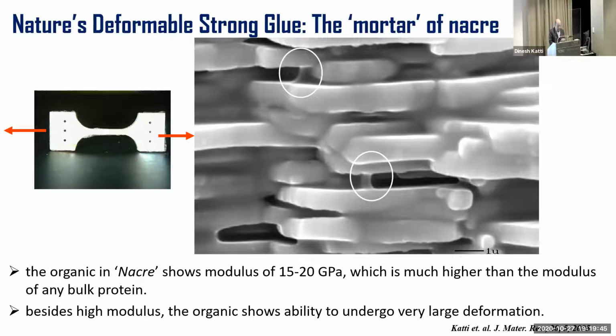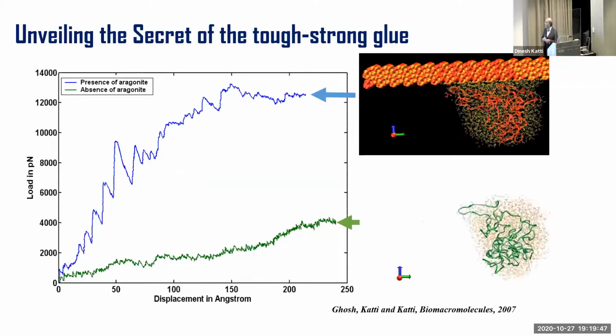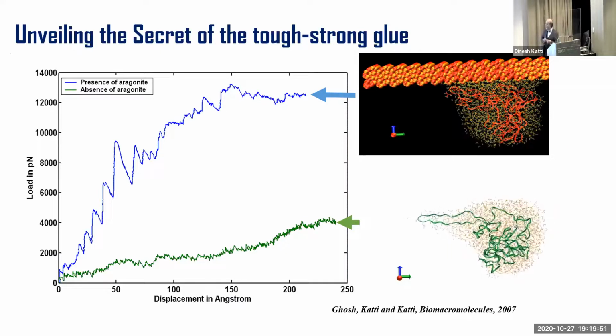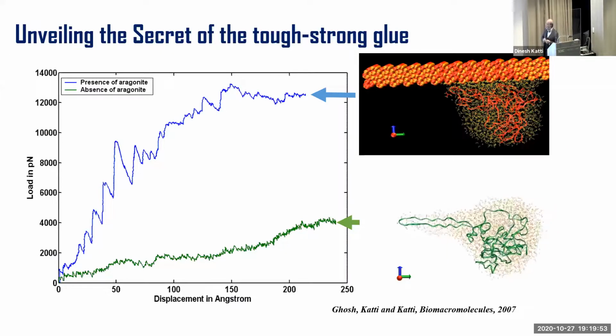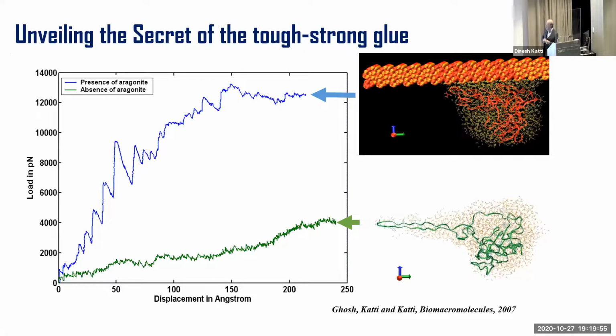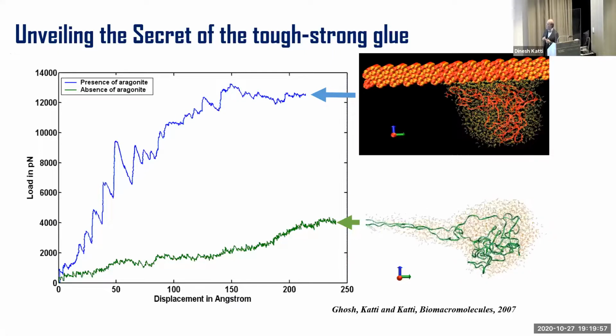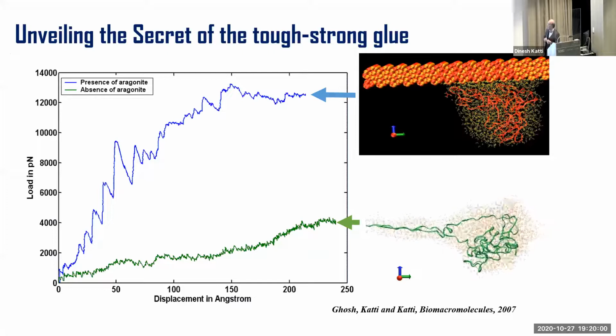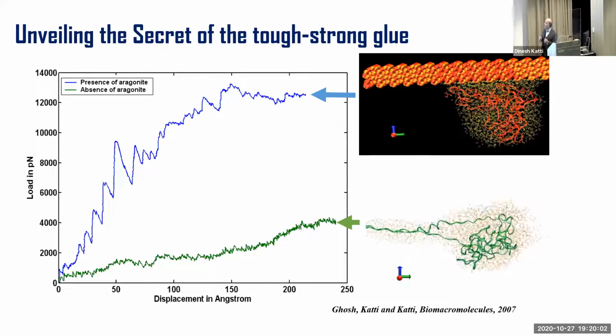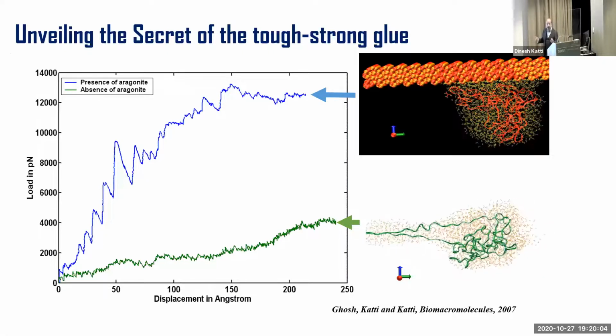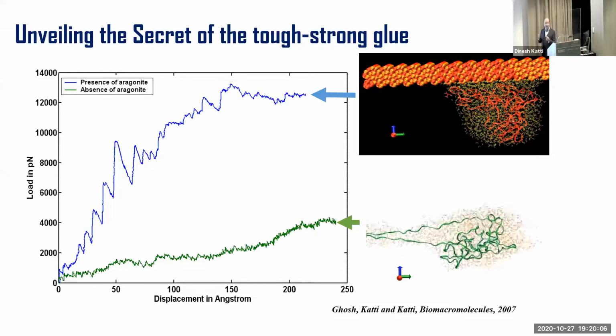And so what we did was we did molecular dynamics simulations where we pulled first the protein by itself. So the green ribbon which you are seeing being pulled is the protein, and we're pulling it by itself. And you can see that this green ribbon is stretching a lot, and that's expected. Proteins, they can stretch a lot. And on the left-hand side, the green curve shows you the load that's needed to pull that protein.